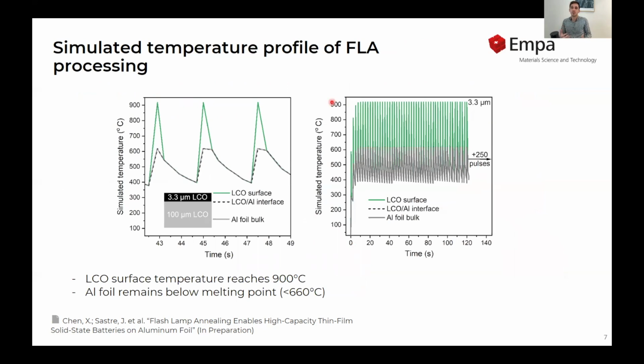Here's a simulation of the temperature profile that is achieved with this flash lamp annealing process. Here the green line shows the temperature at the surface of the LCO. The dashed line is at the interface between the LCO and the aluminum, and the gray one is inside the bulk of the aluminum foil. What we observe is that at the surface, the LCO gets heated up to 900 degrees, which is an ideal temperature for crystallizing this cathode material, whereas at the aluminum foil, the temperature doesn't exceed the melting point of aluminum, which is 660 degrees. And this holds for all the 250 pulses that are used for crystallizing these films.